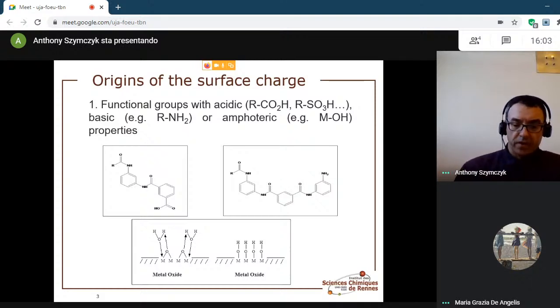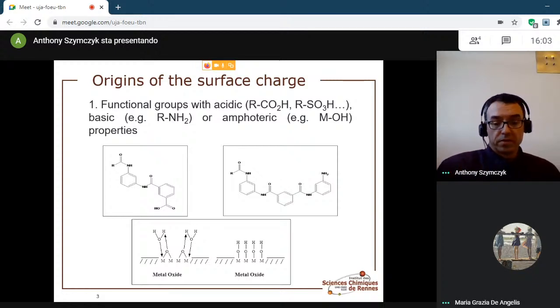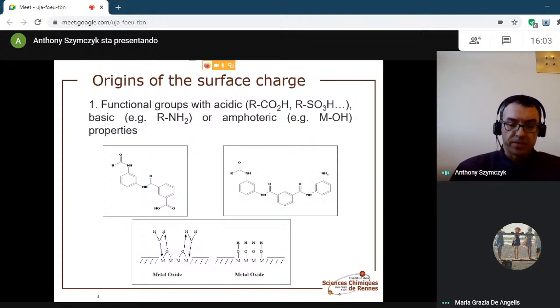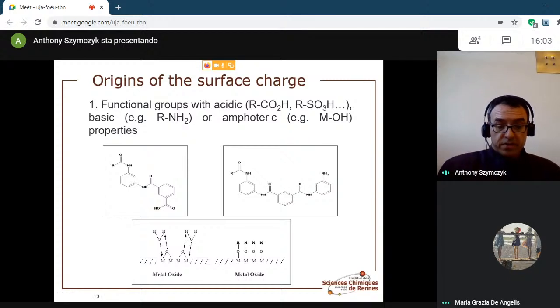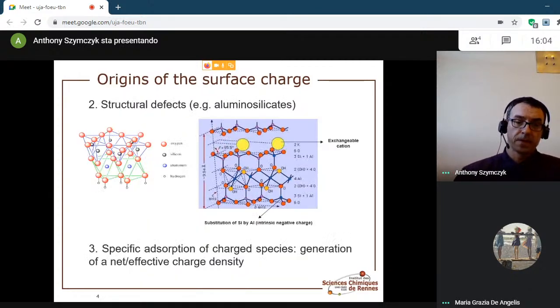So let's start with the various possible origins of the surface charge. The first possible cause is the presence of functional groups with either acid or basic properties, such as carboxylic acids or amine groups. This is the case for many polymer membranes, for instance. We can also find some amphoteric groups on membrane surfaces, such as metal hydroxyl groups present on the surface of ceramic membranes. Structural defects can also be responsible for the surface charge, as is the case, for instance, for clay materials. And last but not least, the specific adsorption of charged species from the solution onto the membrane surface can also lead to an effective charge density.